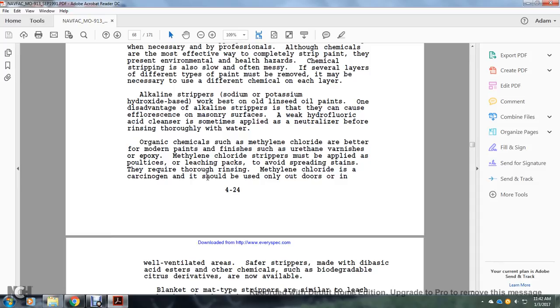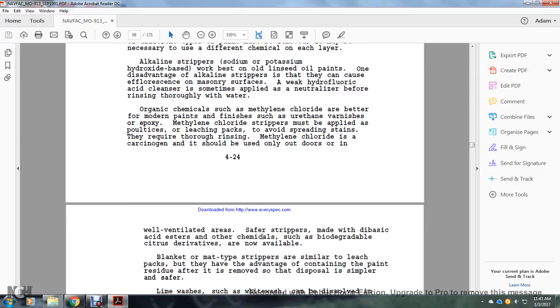Organic chemicals such as methylene chloride are better for modern paints and finishes, such as urethane varnishes and epoxies. Methylene chloride strippers must be applied with poultice and leaching packs, to avoid spreading the stains, and require thorough rinsing. Methylene chloride is a carcinogen that should be used only outdoors and in well-ventilated areas.